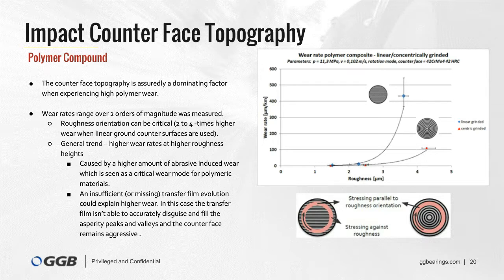So what are the impact factors? We measured two to four times higher wear when the polymer surface was stressed with a linear ground counter surface. For this counter surface, the polymer pin is stressed twice in roughness orientation and twice against the roughness orientation. And stressing against the roughness orientation is seen as the origin for high wear because we induce a lot of abrasive interactions.